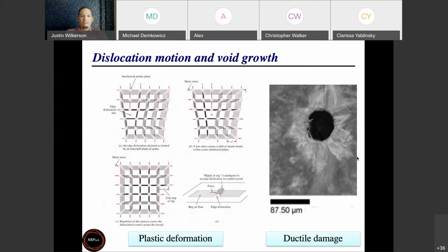Okay, I'm sure in the other lectures you guys have covered this, so I don't really need to talk about it here, but you know that dislocations are line defects in the crystal lattice, and those line defects are the primary carriers of plastic deformation in crystalline metals. As far as damage goes, I've been talking about voids quite a bit as modes of damage, and voids actually grow through plastic deformation of the surrounding material. So you'll have a second phase particle in the material, you debond from that second phase particle, and then you have basically a hole or a void in the material, and then you grow that hole by plastically stretching the material around it.